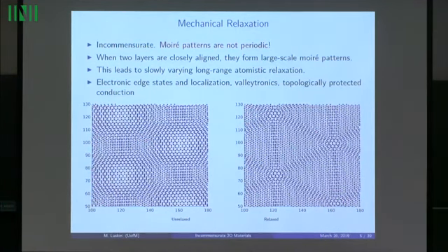So we've actually increased the low energy region, at the expense of creating these sort of domain walls. And these are the AA states, okay? So this is a relaxed pattern. This really is what a real material would actually form, okay?